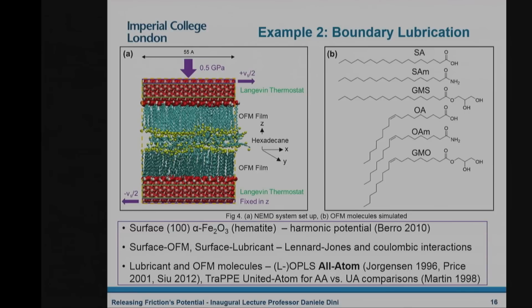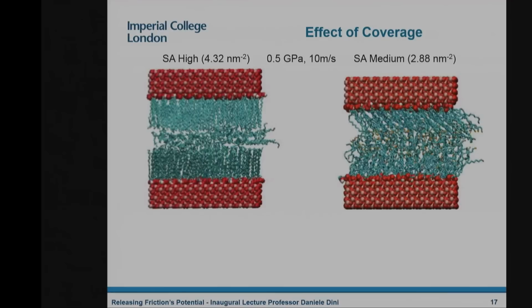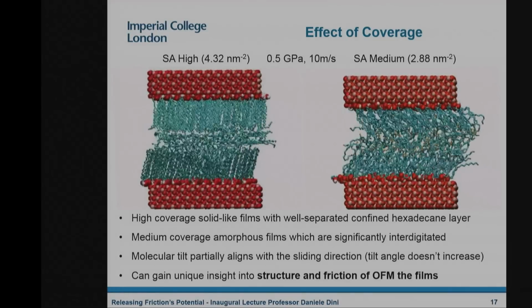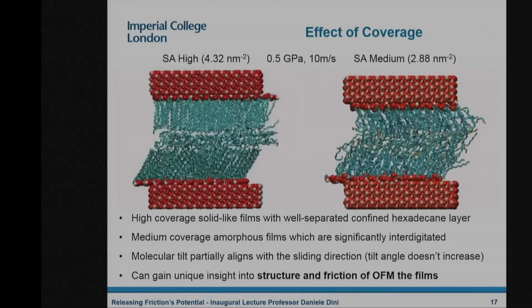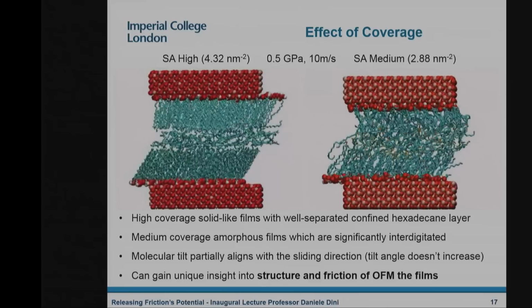Now, what we did, we studied conventional molecules. We started doing a lot of simulations. We did the best we could do with state-of-the-art molecular dynamics simulation. And literally what we wanted to understand is, for example, the effect that how many of these molecules you get on the surface affect the friction. So if I try to put as many as I can squashed on the surface of this molecule, does that help? And the answer comes from the simulation. If you look at this simulation moving, you're applying a load over the surface, you're shearing it, and you're looking at the friction that comes out of these systems.